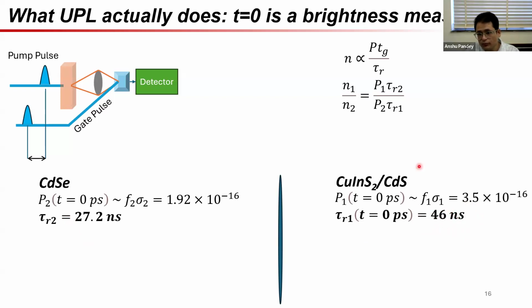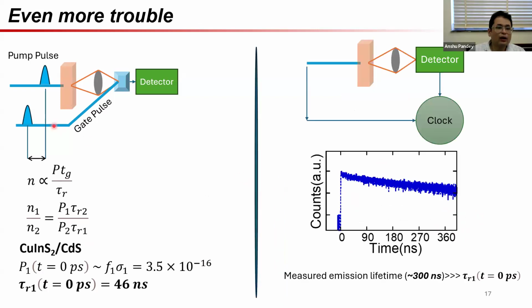Wonderful. Okay, so now, however, let's compare with what we have already seen, and we realize we are getting into even more trouble. Because if my spontaneous emission lifetime is actually 46 nanoseconds, note one thing: my emission lifetime as measured by TC-SPC is far, far longer. This is 300 nanoseconds. So this shows what a ridiculous situation we are in. I'm seeing a spontaneous lifetime at t equal to 0 in the UPL, which is very short, but the emission lifetime which TC-SPC seems to be leading to is very, very long.